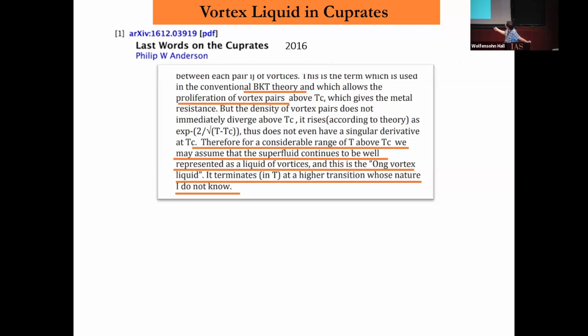So he described all these things. At the end, he said: therefore, if you rise the temperature, you see a considerable range of temperature above TC where we assume that superfluid continues to be well represented, because it's not like the superconducting gap has all closed. And as the liquid of vortex, you still have vortex, you still have a superconducting condensate and a lot of vortex there. This vortex liquid terminates at a higher transition temperature whose nature I don't know. He's saying that I can understand what's going on in the beginning following the KT theory, but then it's something like this.